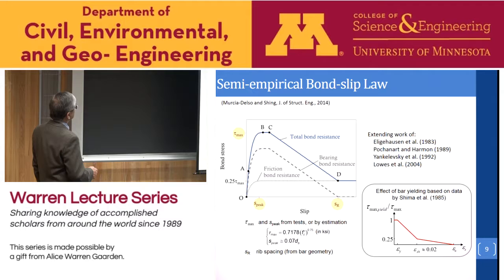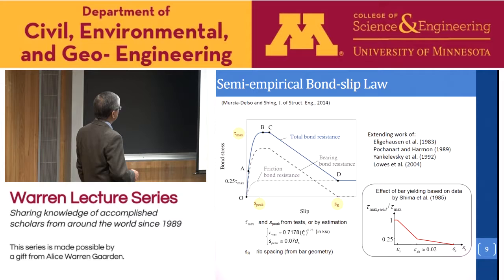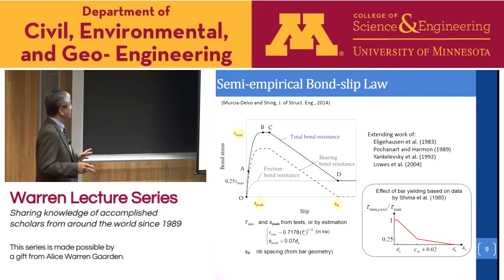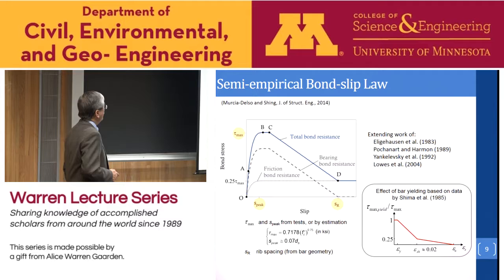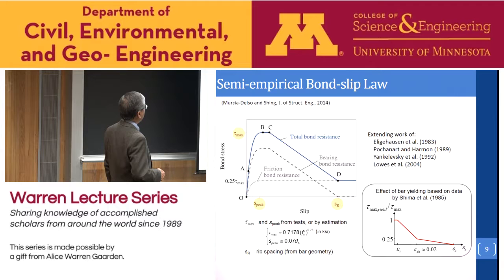Now, essentially, these are physically related. For example, the maximum bond resistance can be related to the concrete strength, and the slip at the peak relates to the bar diameter, and this point is essentially the rib spacing of the bar. So these are only three parameters you can calibrate. And also, it has an empirical law to account for the effect of bar yielding on the bond resistance. So that is based on the test of Shima and his co-workers. So essentially, when the strain in the steel increases beyond yield, then the bond resistance will drop in this manner. So that is also accounted for in the model.